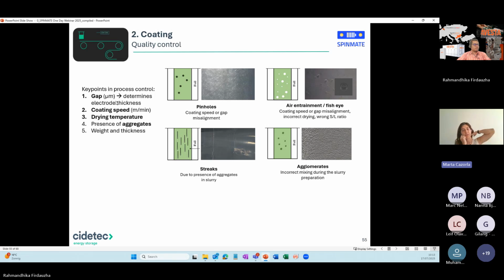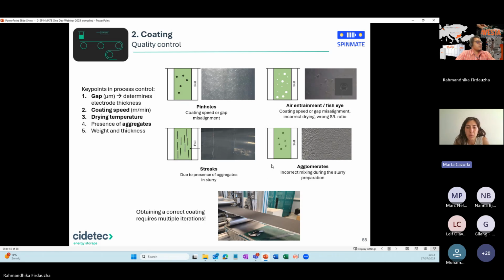But also the coating speed and the drying temperature, because we can have problems such as pinholes, fish eyes, as we call them, or air entrainment, that is causing bubbles, and then streaks, that are because we have maybe some aggregates that then get pulled all around the deposition, or agglomerates, because we could also be having some heterogeneities in our slurry. So these are typical problems that we encounter, and that we need to iterate on till reaching the accurate coating as the ones we've managed to have within SPINMATE.